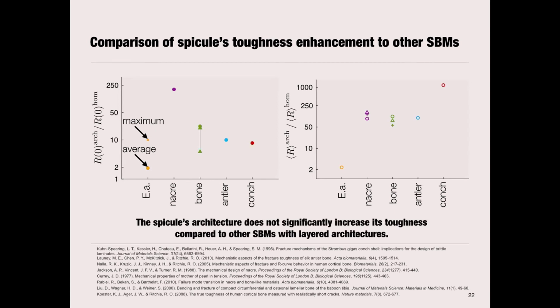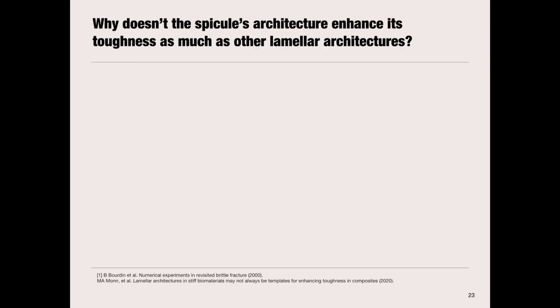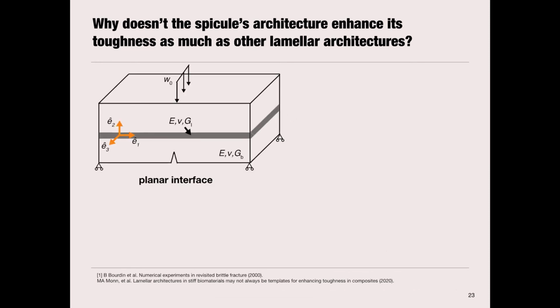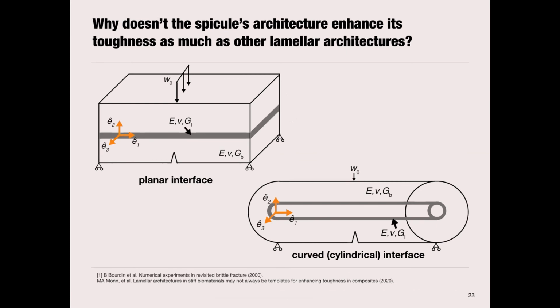And the question we had was why. Why is this material, which many people speculated also has this crazy toughness enhancement, why doesn't it achieve like these other materials? So this was work that I did in collaboration with my batchmate Kaushik Vijay Kumar, where he had developed a phase field model for fracture. We looked at two representative cases. One has a planar interface and one has a curved cylindrical interface, so that the volume of the samples was the same.